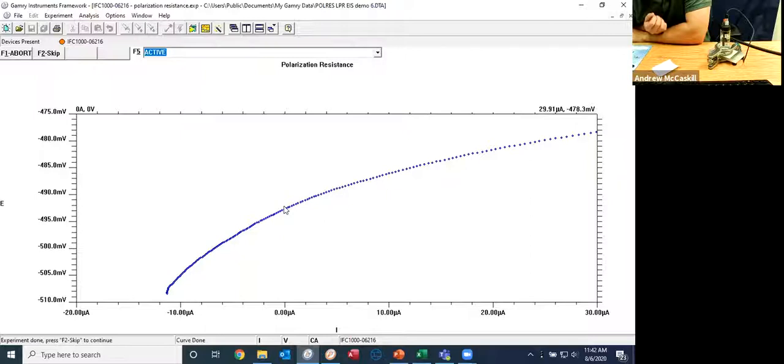That's not the case. It can't be measured with a potentiostat. But what you can do, by use of the Stern-Geary equation and having accurate Tafel constants, is figure out what this corrosion current is relative to the OCP value.